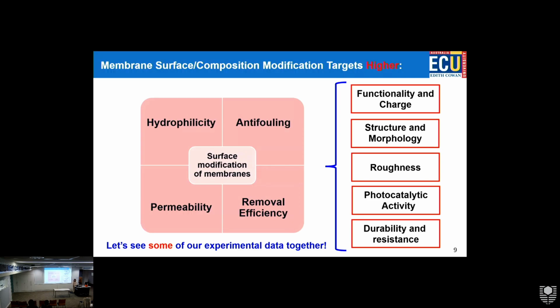So if we increase the hydrophilicity, we basically increase the water-loving affinity as well as reduce the fouling tendency of the membrane, because the contaminants cannot attach to the surface, basically. And it will indirectly affect the lifetime because we don't have to do that much cleaning, basically. So anti-fouling, we want to increase the anti-fouling properties. This hydrophilicity improvement indirectly affects that. And we want to enhance the permeability, so we produce more water while we also reject unwanted contaminants and improve the overall efficiency of the process.